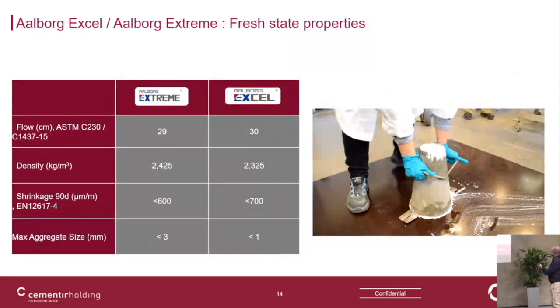So with the fresh properties, as said, the flow is very important. You have with the small cone method a spread of 29 centimeters up to 30, so there's not a lot of difference between the two products. About density, the Aalborg Extreme is a little higher because of the maximum particle size, and then also the shrinkage we measured is lower values than traditional UHPC.